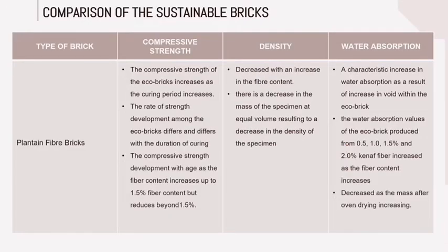There are some comparisons that we can make based on these three sustainable bricks. Firstly, plantain fiber brick. Comparing the compressive strength, this ecobrick increases as the curing period increases. The rate of strength development among the ecobricks differs with the duration of curing. The compressive strength developed with age as the fiber content increased up to 1.5% fiber content, but reduced if the fiber content went beyond 1.5%. So from the density, plantain fiber brick density decreases with an increase in the fiber content.